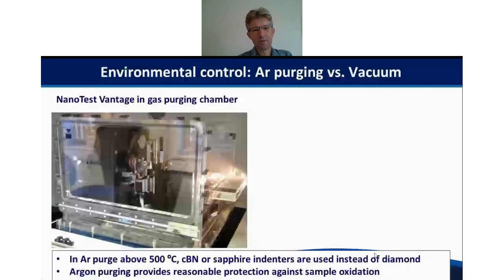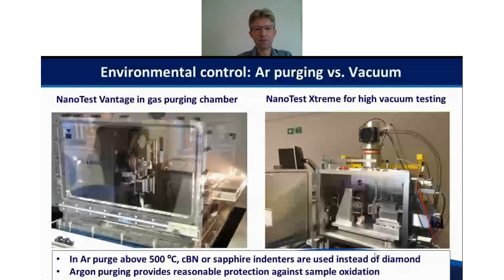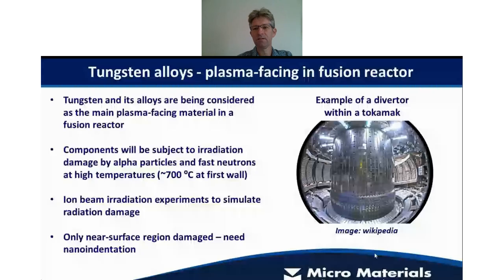So up until now, I've been talking about controlling, basically eliminating almost all the oxygen with an argon purge. This is particularly effective in most cases, and if we want to test over 500, we combine it with testing with CBN indenters. For some materials, particularly superalloys, we use sapphire indenters instead to avoid chemical reaction, and it's a particularly effective solution in most cases. But in some cases, we need to go towards high vacuum, because we really need to have no oxygen there at all. And this is an example on the right showing a nanotest extreme. The inside of one, you can see the design's a little bit different to allow for this high temperature testing in vacuum. And this really can negate any sample and indenter oxidation issues.